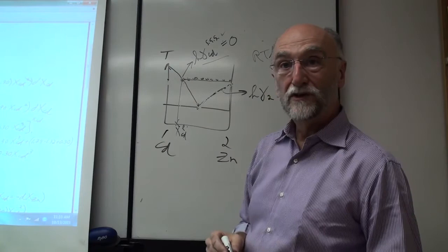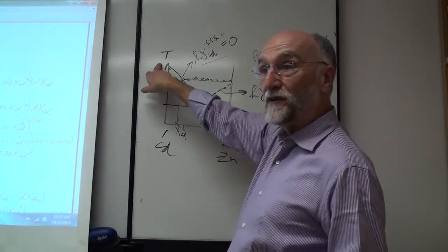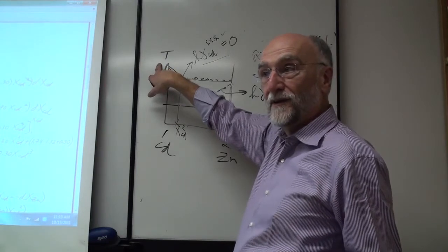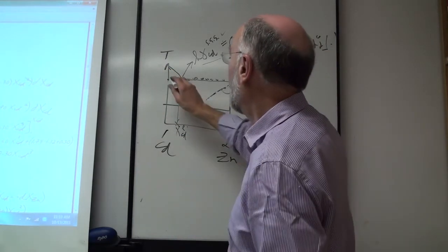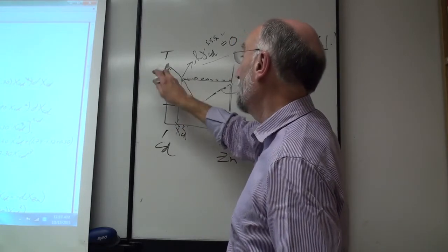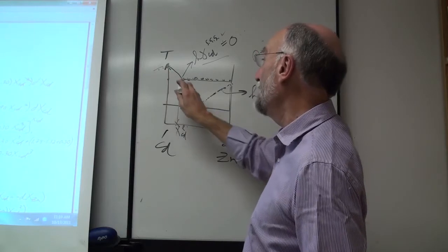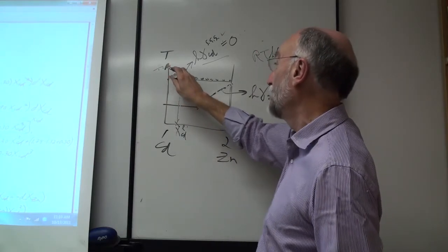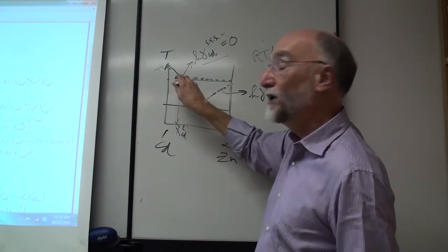So the activity coefficient with respect to solid cadmium is 0, and if I know the heat of fusion of cadmium, I can correct for the standard state change. Or, the other way of looking at it: if I know the heat of fusion of cadmium and I know this liquidus composition, then I can solve my RT log gamma equation to get the activity of cadmium here, so that becomes my endpoint.